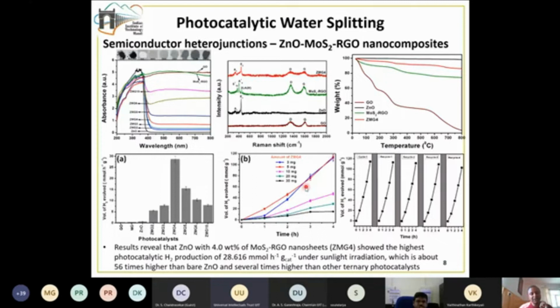Even we can get very good hydrogen evolution just with 3 milligrams or 5 milligrams. And when we further increase the amount of the catalyst for this reaction, the activity decreases, due to the aggregation of the catalyst. So when the catalyst aggregates, the effective surface which is exposed to the sunlight gets minimized, and that's the reason it is not so effective.